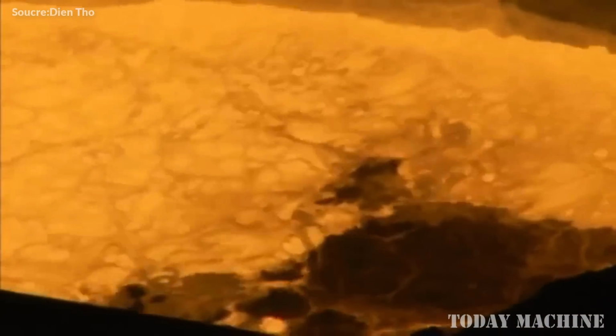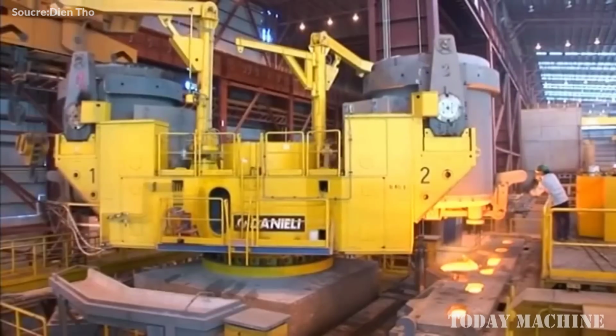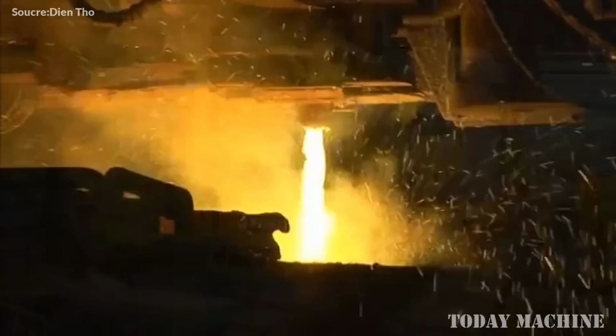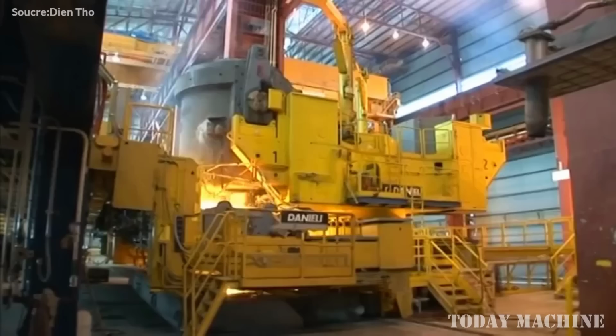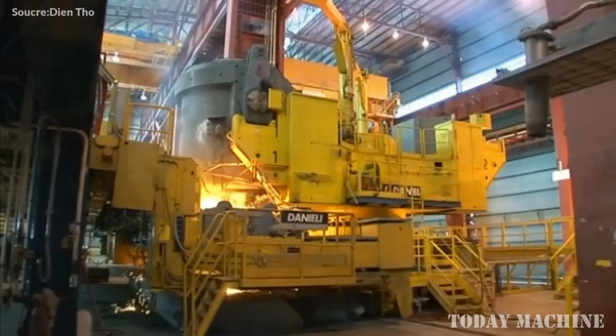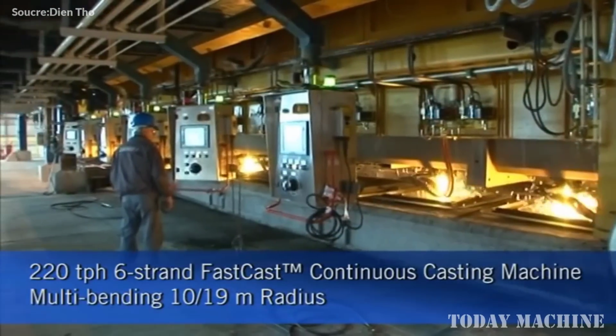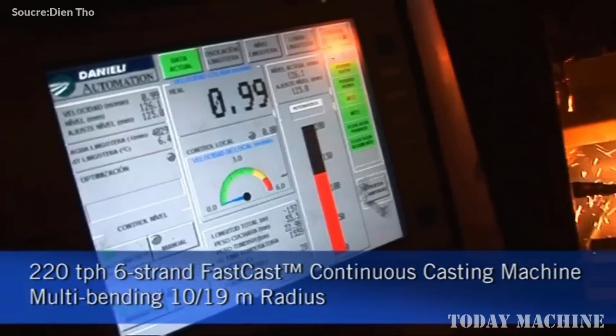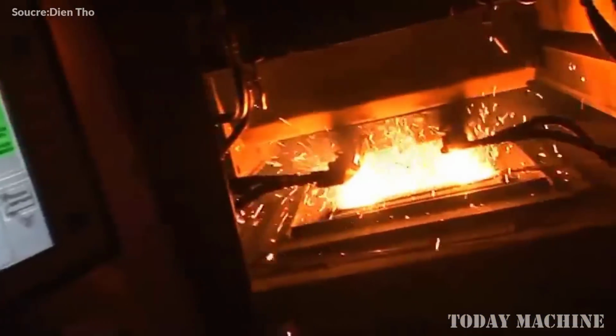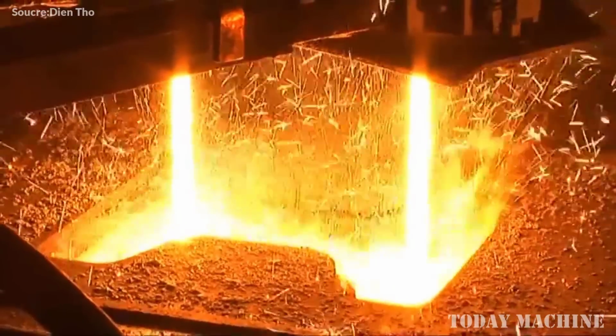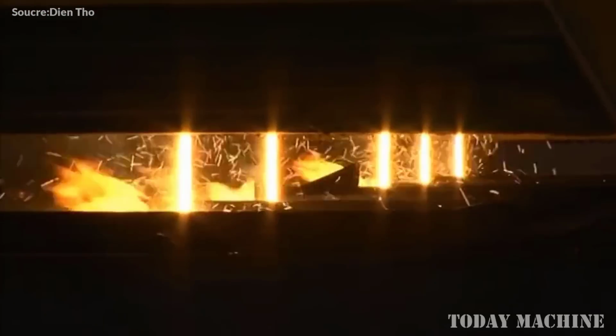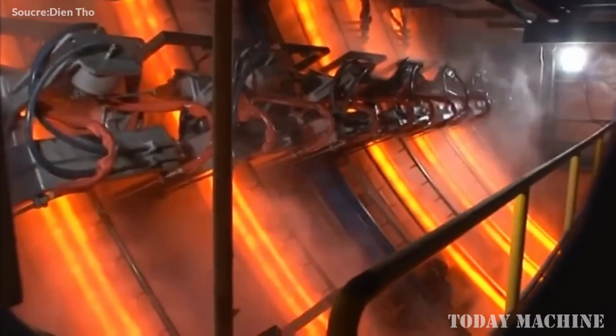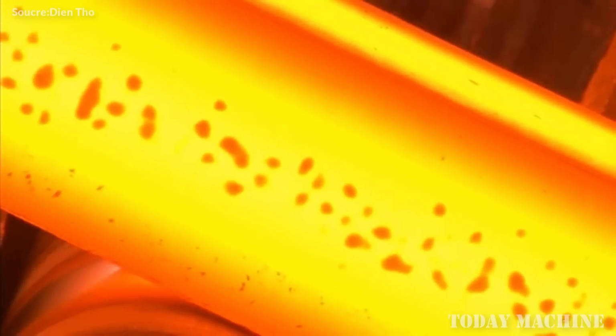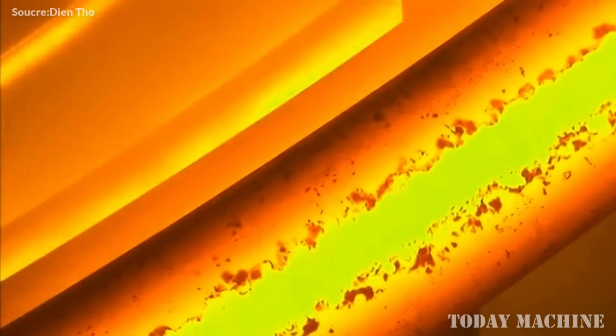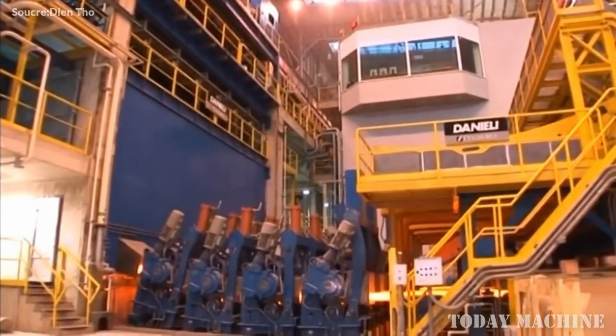This machine is a 6-strand continuous caster that incorporates a multi-bending 10/19 of a meter radius design, enabling efficient casting of billets and beam blanks with a high level of precision. This multi-bending approach reduces stress on the steel during casting, which enhances the quality of the final products. The fast cast can produce beam blanks ranging from 280 by 220 by 90 millimeters to 610 by 320 by 100 millimeters.